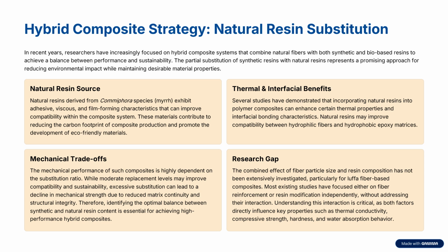We also have a mechanical trade-off. The mechanical performance of such composites is highly dependent on the substitution ratio. While moderate replacement levels may improve compatibility and sustainability, excessive substitution can lead to a decline in mechanical strength due to reduced matrix continuity and structural integrity. Therefore, identifying the optimal balance between synthetic and natural resin content is essential for achieving high-performance hybrid composites.